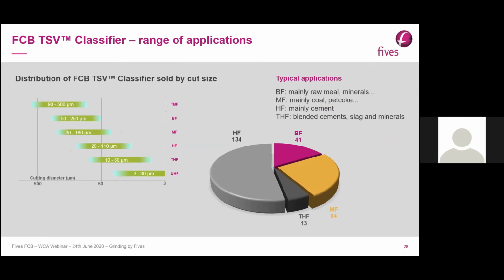The geometry of the classifier, the height of the classifier, depends, in fact, on the range of fineness which are the targets. And we start from the TBF, what we call the TBF, the very low fineness, with cut size between 90 to 500 microns, down to the ultra high fineness from 3 to 30 microns cut size. You have the split of the different types on the left here. The main portion comes with HF TSV, which are in cement grinding plants.